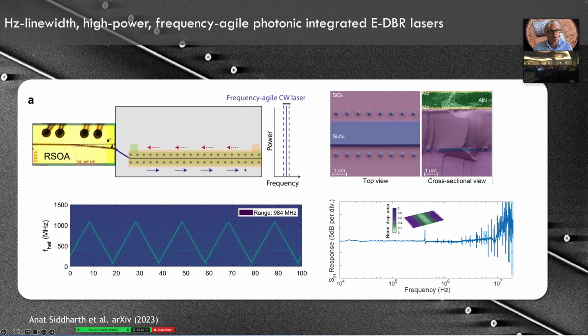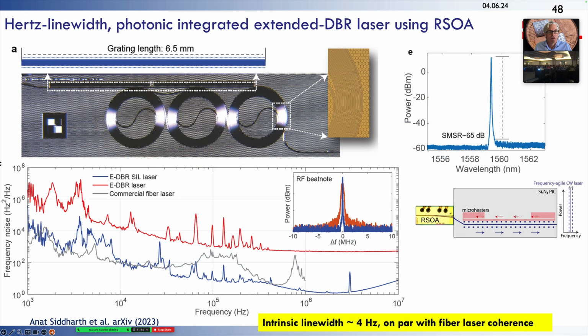And in recent work also by Snehal Bava, we have shown that if you directly have an aluminum nitride actuator on top of a simple grating, we can again get very good actuation bandwidth up to well beyond a megahertz, and create very, very compact lasers that in themselves have line width of typically a few kilohertz, but that can become hertz level line width by self-injection locking them to long spirals. And so this is an example of an extremely cost-effective device.